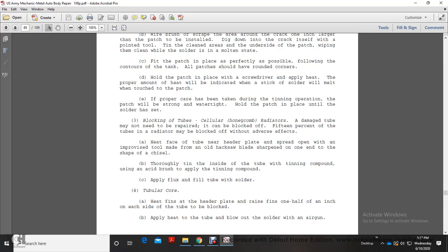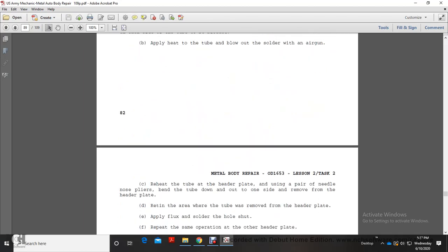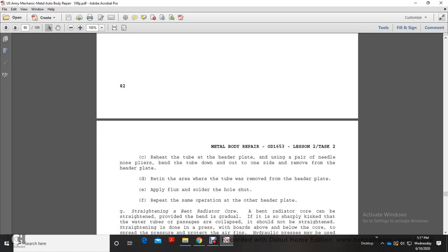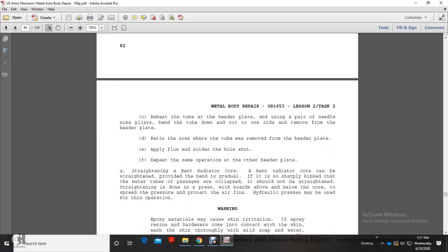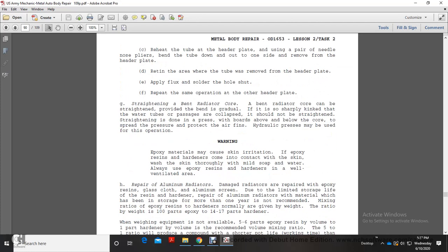Thoroughly tin the inside of the tube with a tinning compound using an acid brush. Apply flux and fill the tube with solder. Heat the fin to the header plate, and raise the fin 1/2 of an inch on each side of the tube to be blocked. Apply heat to the tube and blow out the solder with an air gun. Reheat the tube with the header plate, using a pair of needle nose pliers to bend the tube down and out to one side, and remove it from the header plate. Retin the area where the tube was removed from the header plate, apply flux and solder the hole shut, and repeat the same operation on the other header plate.